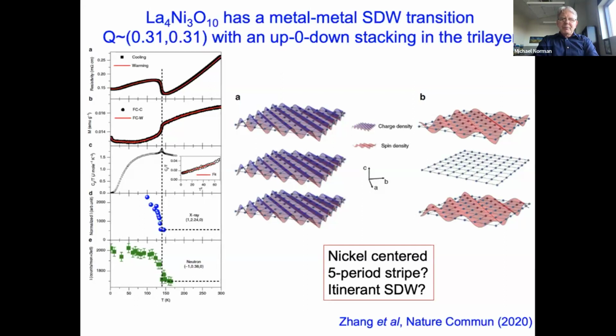Charge and spin turn on at the same temperature. They both look like they have an order parameter-like dependence. So it's not like chromium, where the charge is secondary to the spin. It looks like the charge and spin are turning on at the same time with more or less an order parameter-like variation. This is unlike cuprates, where spin and charge seem to be separated in temperature. And again, you have a very pronounced specific heat anomaly, very comparable to what you see in 214 nickelates when they go into the stripe order phase. Resistance has a pronounced anomaly at the stripe order transition, but it goes from a metal to a metal. So it's a metal to metal phase transition.